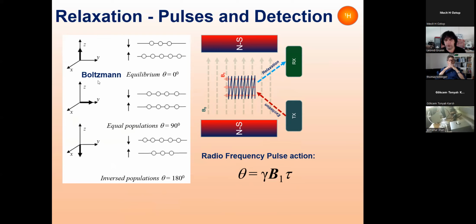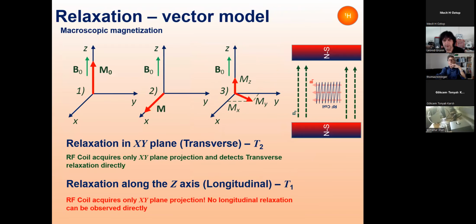From the geometrical point of view, in equilibrium the majority looks along the z direction. Normally, z is the direction of the magnetic field. When you make these populations equal, there is no z component, because these guys just look somehow perpendicular to the magnetic field and experience precession. Or when you apply the inversion pulse from the transmitter, the populations are inverted. The rotation of this vector is proportional to the magnetic field of the transmitter that we apply to the coil. I need to say this faster, because we will come soon to the applications, but this is extremely important. We can rotate the total magnetization of the sample. You put the paramagnetic sample, which is most of the possible samples, in the magnet, and it is being magnetized.